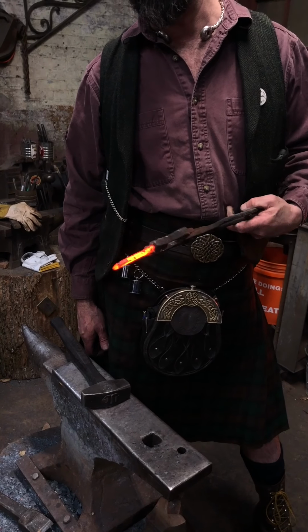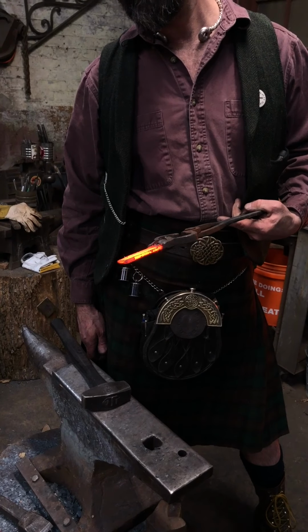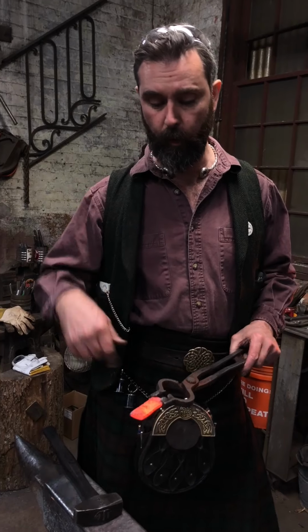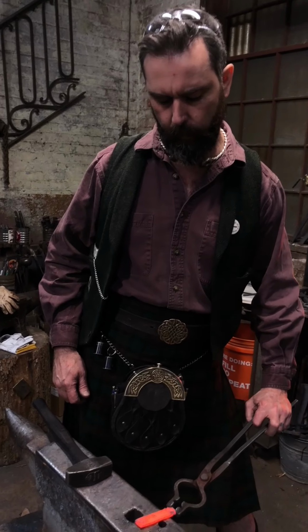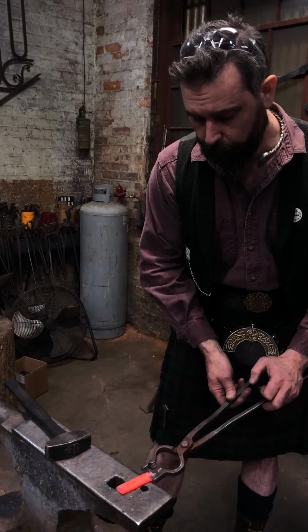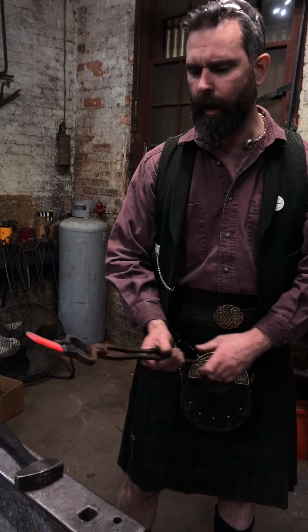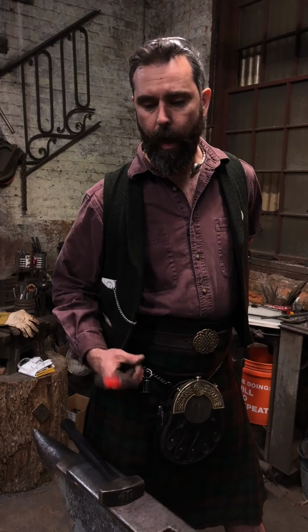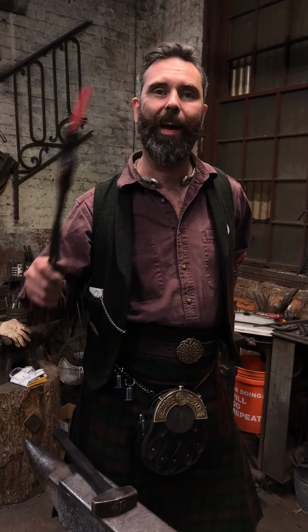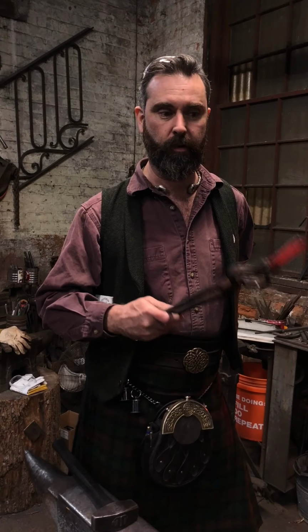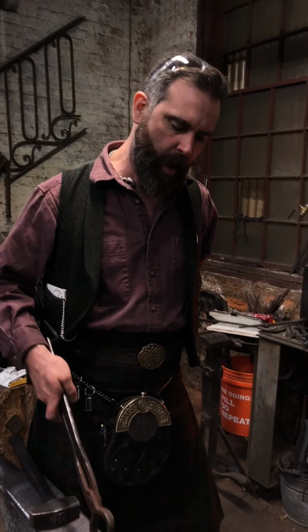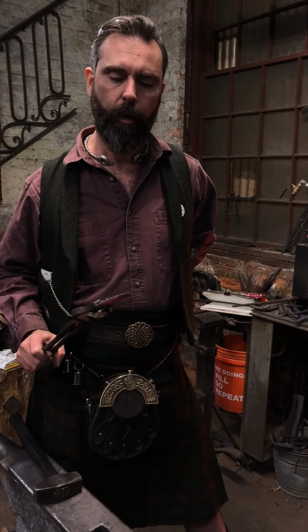Probably could have forge welded that if I fluxed it up. So I'm going to let that cool down and then bring it back one more time and do a break test on it, quench it, do a break test on it. And we should have a good fat grain structure again. The reason I'm cooling it down is to show that it's not the quench at high temperature that causes the large grain, but instead it's the actual time of it sitting in the fire that develops the large grain.